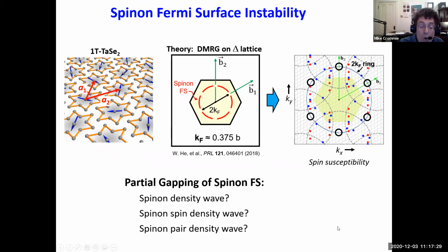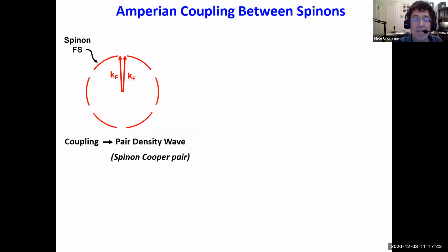So I'm going to walk you through the spinon pair density wave and explain how this can explain our experimental results. So how does a spinon pair density wave occur in this material, and how might it actually explain what we see experimentally? First, you have to understand what a pair density wave is. A pair density wave is basically a Cooper pair that has finite momentum. The idea is that in a superconductor, you usually have the plus and minus k that creates the Cooper pair. But for a pair density wave, they're both pointing in the same direction. And so a spinon pair density wave is basically spinon Cooper pairs with finite momentum.